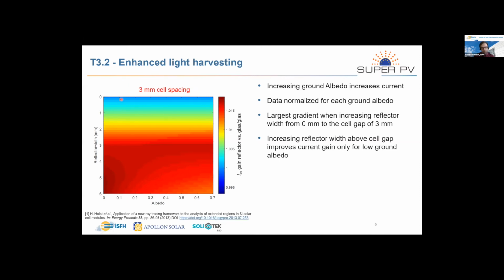And then when we start increasing the size of the reflector in the simulation, we see that we have a rather steep gradient up to the cell spacing of 3 millimeters. So here's the first broad optimum, you can say, which is very homogeneous for all albedos. And then when you further increase the reflector size, you see that for a very bad albedo, the gain increases. But if you consider a higher albedo, the gain slightly reduces again, because you simply shade the rear side of your cell in the bifacial module.